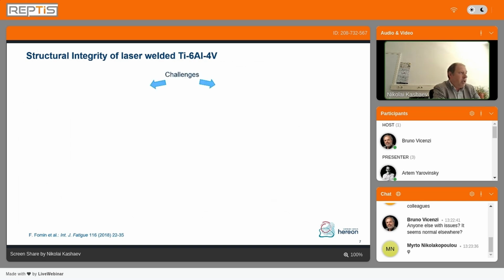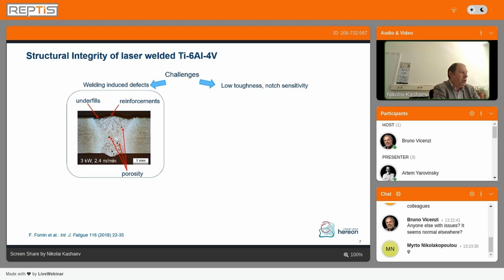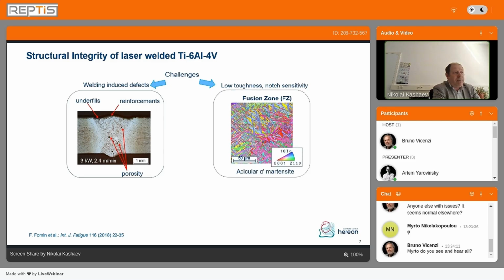First of all, for general understanding, if we do laser beam welding, we have a number of challenges. We produce welding-induced defects, such as internal porosity, and we can also have geometrical defects, imperfections, or reinforcement. Another challenge is we have complex microstructure, and typically due to high cooling rates, we obtain an acicular martensitic microstructure, and therefore we have low toughness, and titanium is well known as a material with a high notch sensitivity. We have even increased the notch sensitivity. And these are inevitable results of laser beam welding and also additive manufacturing processes. We can optimize, but we cannot completely eliminate the presence of defects.